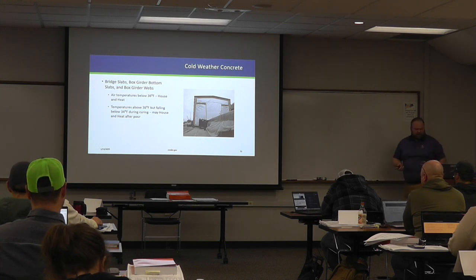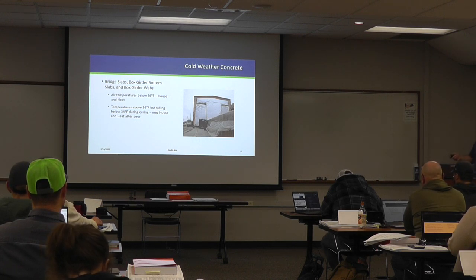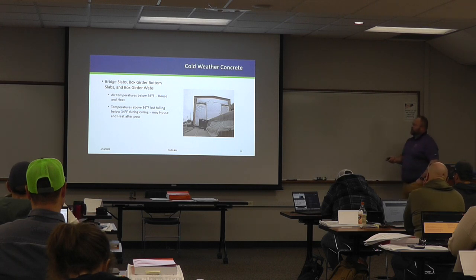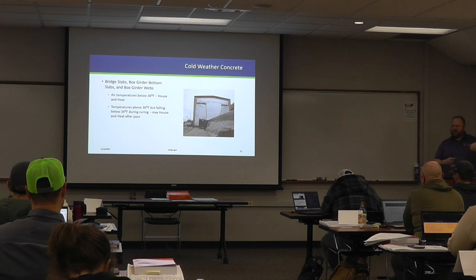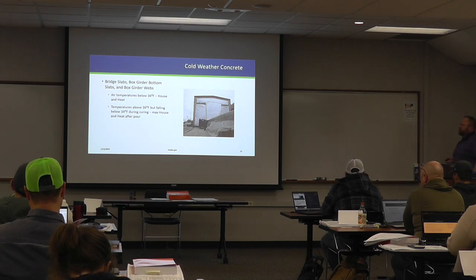Now, the one thing to think about if you are in this and you're using a combustion source of heat, we want this to be exhausted outside of the housed area. If we're exhausting the combustion source inside the housed area, you can lead to rapid carbonation of the surface, which ends up with a dusty, chalky feeling on the surface. That's from that carbon dioxide reacting with the concrete. So it needs to be exhausted outside of the housed area if you're using a combustion source for heat.